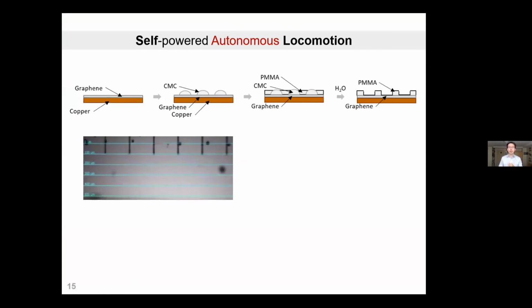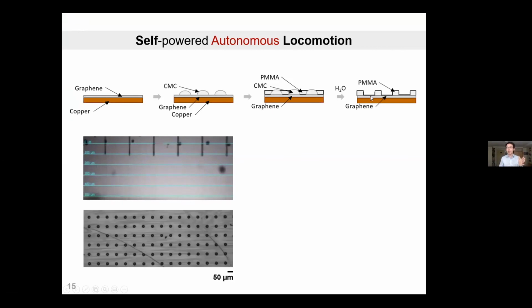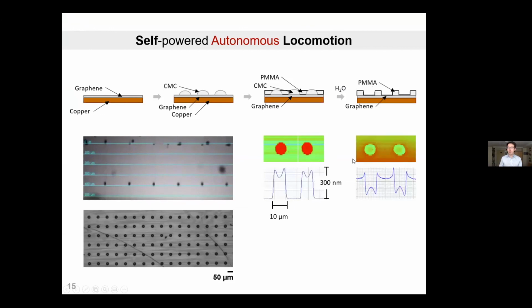So here, what I'm showing is basically, instead of just doing this very simple sandwich structure of graphene or 2D material polymer graphene, you can actually modify this fabrication a little bit using what is known as carboxymethylcellulose, or CMC. This is a water-soluble polymer. So if you print this instead of the usual polystyrene or other polymeric material, we can create a fabrication method that allows us to pattern these microwells within our PMMA underwater dissolution. So these microwells are basically 10 microns in diameter and maybe 100 nanometers thin, followed by the surface profile